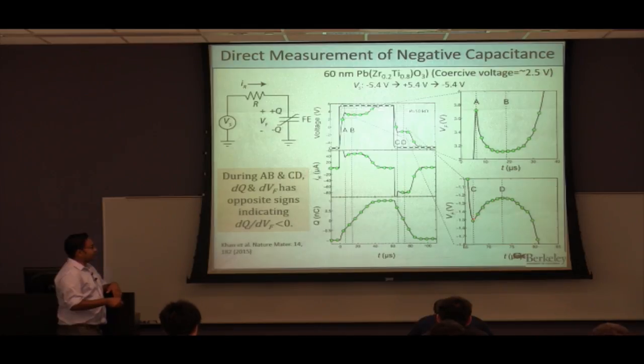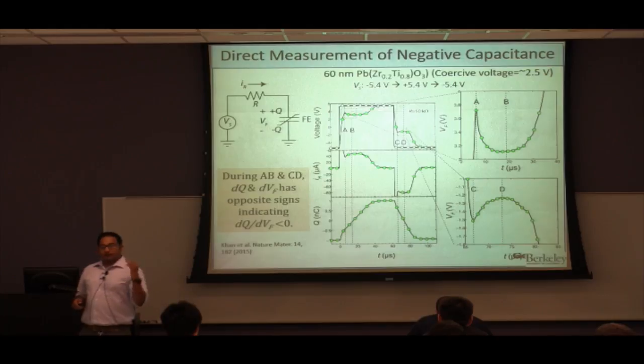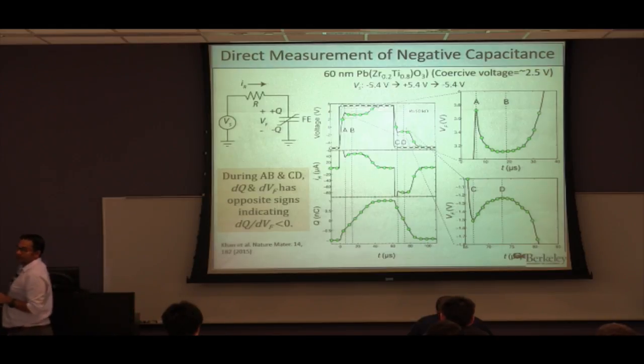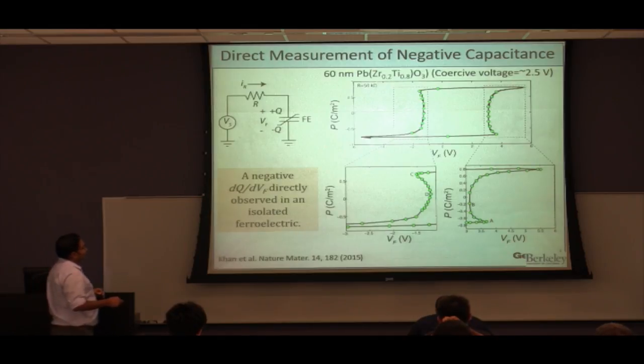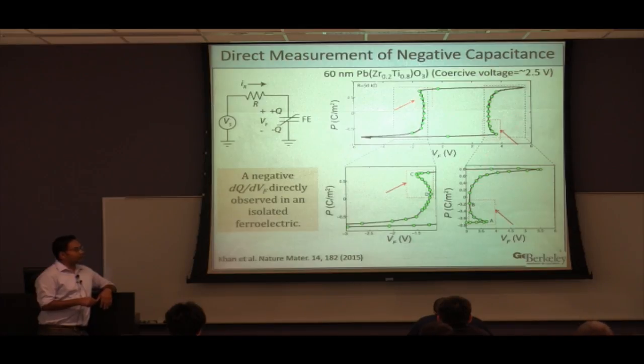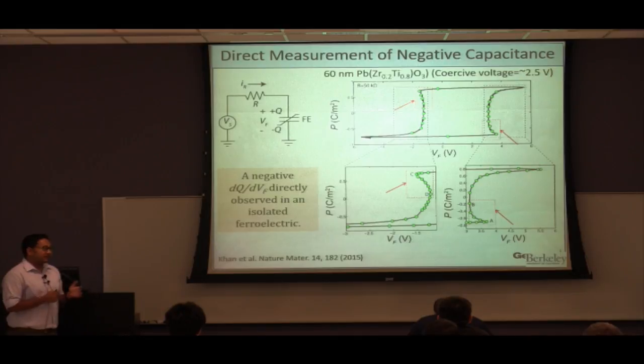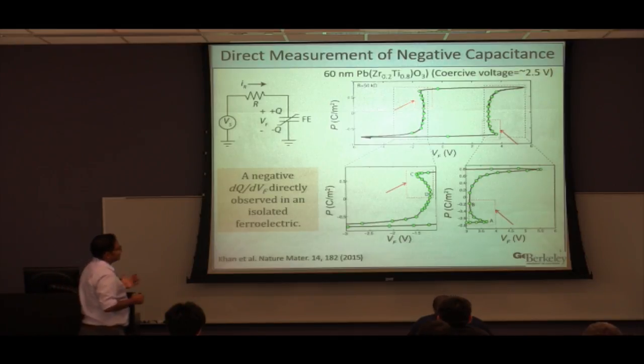The voltage is increasing in this case, while the charge is decreasing. So from these measurements, we can plot the charge and the voltage. And if we plot the charge and voltage, what we can clearly see is that there are certain regions where the slope of this charge voltage curve is negative. And this is actually the first time a negative capacitance was directly measured in a ferroelectric material.